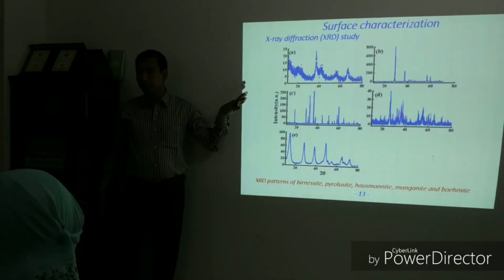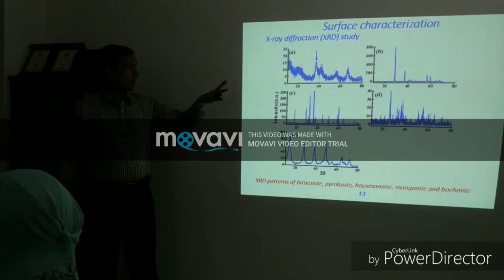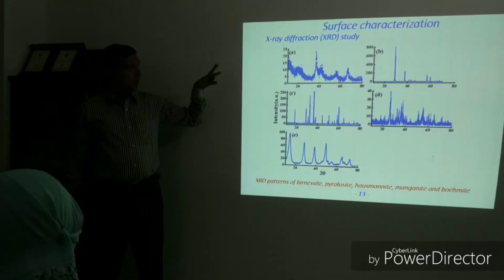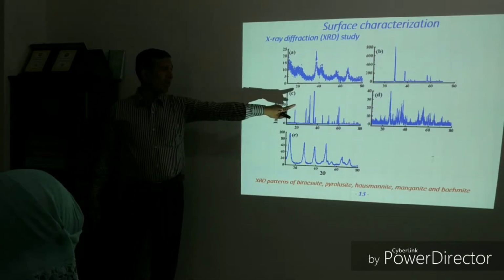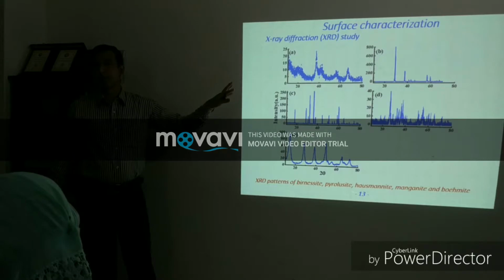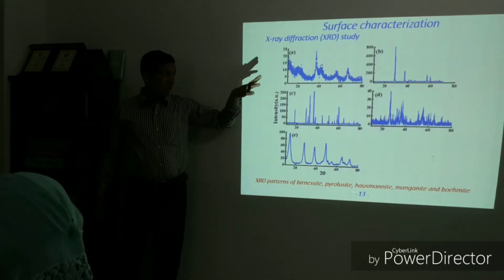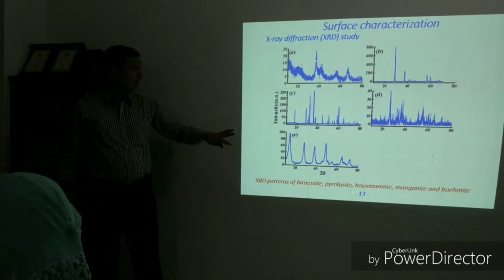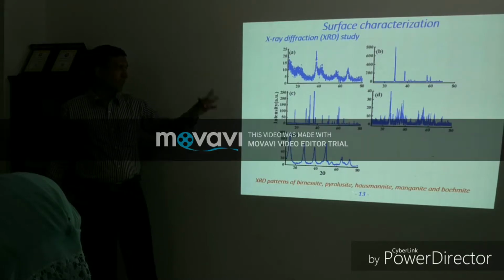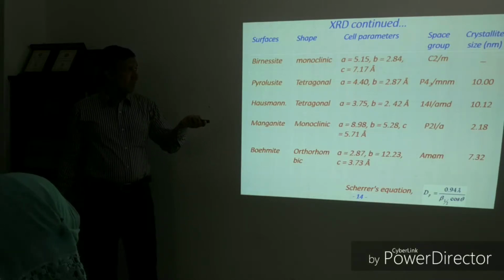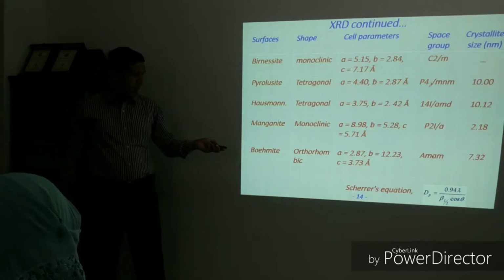Then surface characterization, XRD. So these are the typical XRD patterns for birnessite, pyrolusite, hausmannite, manganite and boehmite. From this spectra, it is clearly seen that for birnessite and manganite, the peaks are relatively broad and not too intense. This indicates that these two substrates are amorphous in nature. On the other hand, in case of pyrolusite, hausmannite and boehmite, peaks are relatively intense and sharp, indicating crystalline nature. And here I have included the results for XRD. From this we can see the crystalline size for these surfaces, which have been calculated using Scherrer's equation.